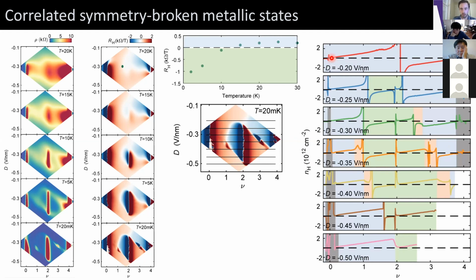The Hall density grows as we dope, and then abruptly changes sign as we cross the Van Hove singularity, and then shrinks back to 0. So this blue colored region indicates that we think there is standard fourfold degeneracy of these bands. But within these green colored regions, as we start pushing into this halo, you can see that the sign of the Hall density abruptly inverts from what it should be from a single particle model. And then as we push into these replica halos at 1/4 and 3/4 filling, we get yet another inversion.